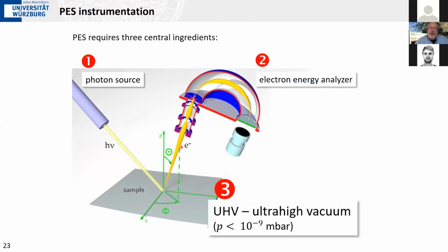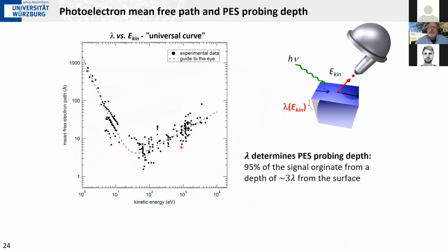Okay, and finally, vacuum. Why is vacuum so important here? And that is related to a property that I haven't addressed before. You excite electrons typically somewhere within your sample, but you want to detect them in the vacuum, so they have to come out of your sample. So they have to travel towards the surface. And on the way towards the surface, they will undergo inelastic collisions with other electrons and create interband transitions or plasmon excitations of the electrons in my solid.